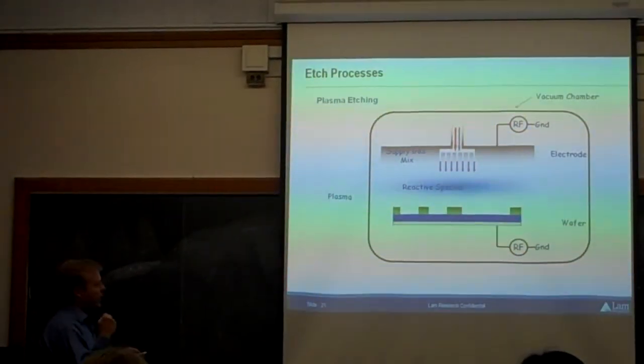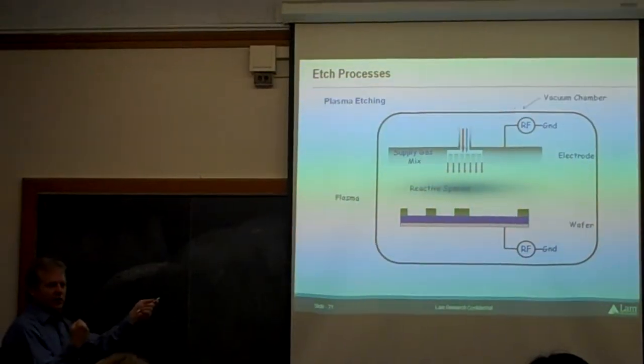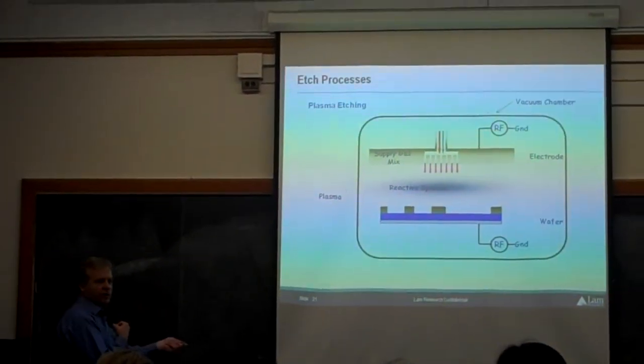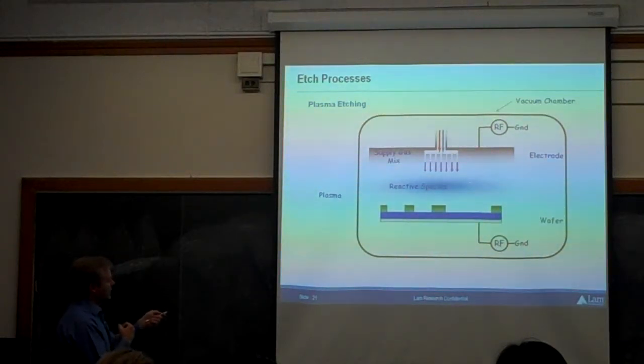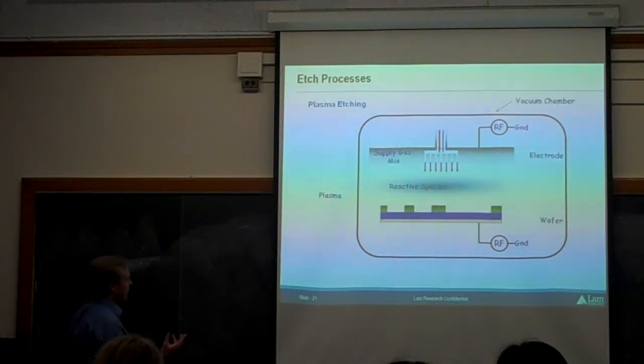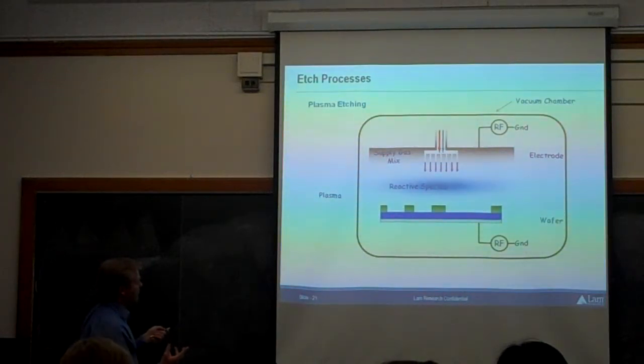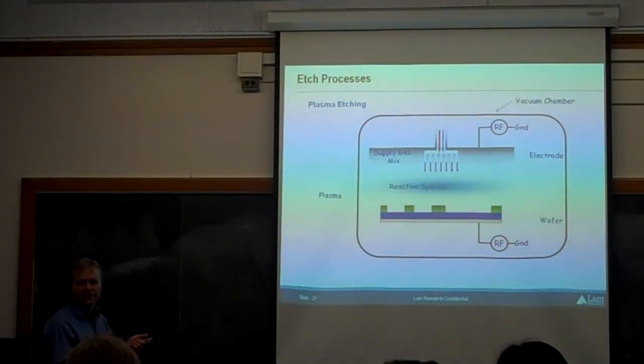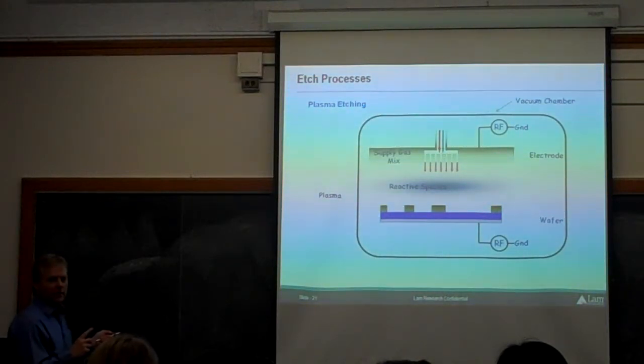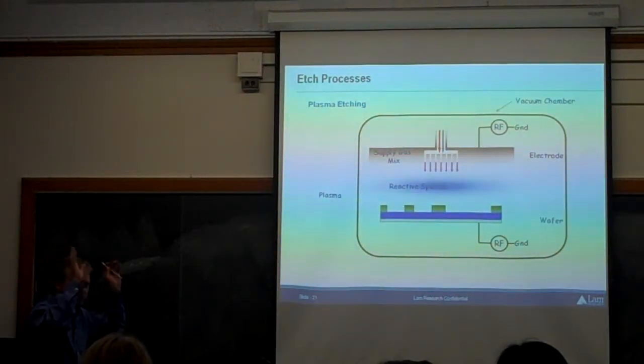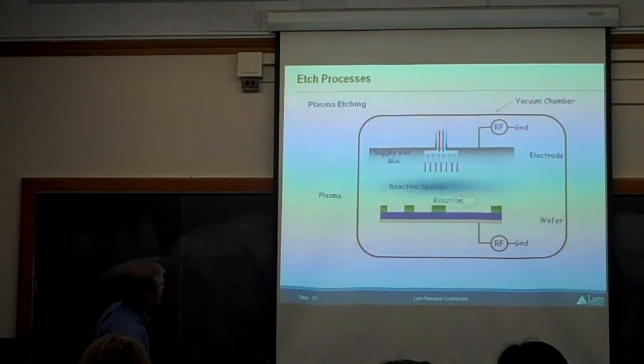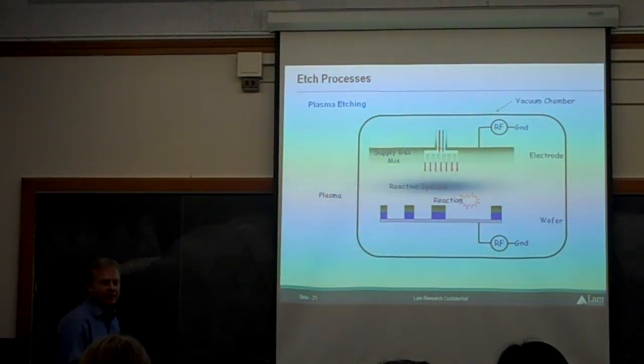And I'll have Cl+ and an electron floating around, and O+ and an electron floating around. And that's all in this soup up here. And then I use the power down here to accelerate those ions down to the surface. If you pick your gas, this is what chemists and chemical engineers do, you have to experiment and figure out what gases have reactive species that will etch the blue. That's actually pretty easy, but the problem is I can't etch the green. Because if I etch the green, that goes away and I don't have my mask anymore, and everything's gone. So it's not as easy as it always seems, but in PowerPoint it's great.